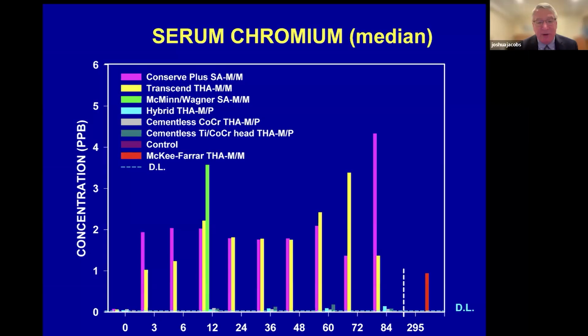And this represents studies we've done at Rush over many years. This was an NIH-funded study where we prospectively followed a number of individuals that had different types of joint replacement. And to summarize this complex slide, the normal value of serum chromium in individuals who are healthy, with normal renal function, and don't have an implant is about 0.3 parts per billion, or nanograms per milliliter. So that's the unit we use, parts per billion. But if you have a conventional metal-on-polyethylene bearing, and that's in these boxes here, you have maybe a 2 to 4-fold increase. But if you have a metal-on-metal bearing, even if it's well functioning, you may have a 10 to 20-fold increase in the amount of metal that we're measuring in the serum.